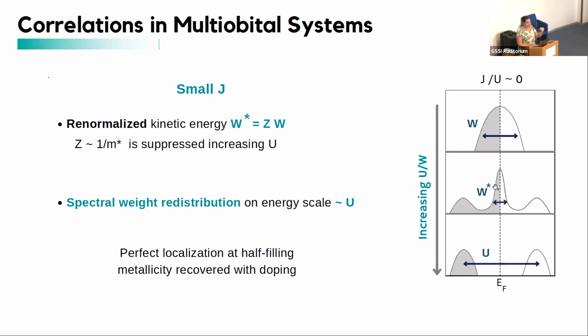So as I increase U, you see that I have mainly two effects. One is the reduction of the kinetic energy of the coherent peak. And this reduction can be encoded in this Z factor, for example, that is a measure of the effective mass essentially. And the other aspect that is changing is that I'm moving spectral weight from the coherent peak to the Hubbard bands.